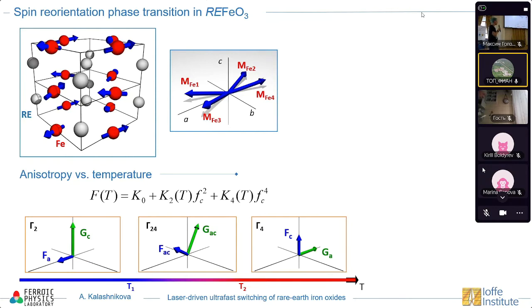And what is important is that apparently in this material, anisotropy is very sensitive to the temperature. Below the Néel temperature, which in these materials is above 600 K, we have a weak ferromagnetic moment pointing along this axis. It's the C axis of the crystal.